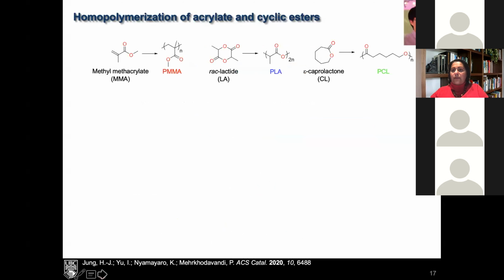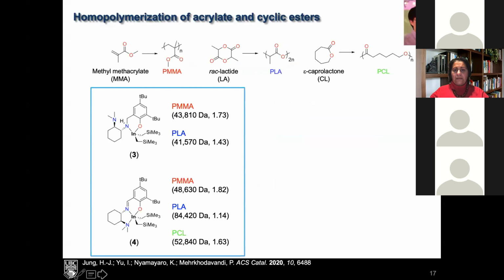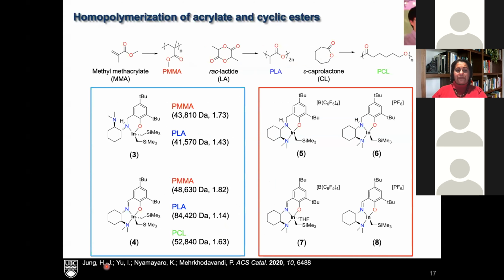So this is work by June Jung, who's a current graduate student in my group. And what he did was he first of all looked at the homopolymerization of methyl methacrylate, lactide, and caprolactone with a number of different systems that we had in our group, both neutral. So in this case, these two are neutral indium compounds, indium alkyl compounds, slightly different. One of them has an amine and one of them has an imine linkage. And then cationic analogs where we have amine or imine ligands, and we have different counterions.